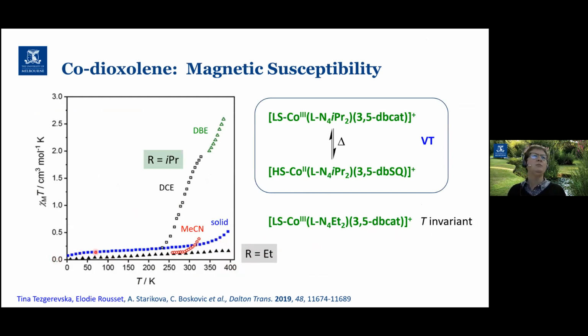On the other hand, the blue squares here are the isopropyl analog, and that's in the solid state. You can see above room temp, it's essentially diamagnetic at low temperature, and then above room temperature, there starts to be an uptick. So in fact, it looks like in that isopropyl analog, we're starting to see some kind of interconversion. And from those chi-T values, that looks to us like a valence tautomeric interconversion, not a spin crossover interconversion.